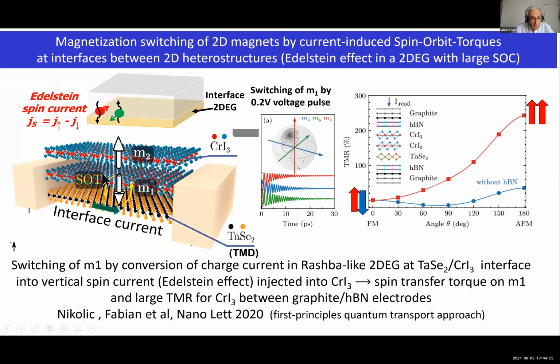And so what I want to say is, what can be the exploitation of the spin orbit in a 2D magnet? At the interface of a 2D magnet with a normal metal, there is the possibility of exploiting the 2D electron gas at the interface between the two materials, or between two types of 2D magnets. And so the spin orbit effect that can be expected at an interface, in the two-dimensional interfacial gas, is what is called the Edelstein effect.